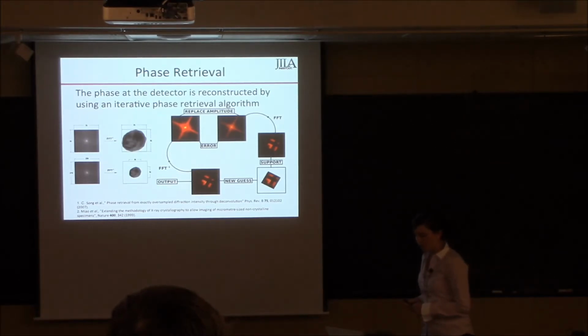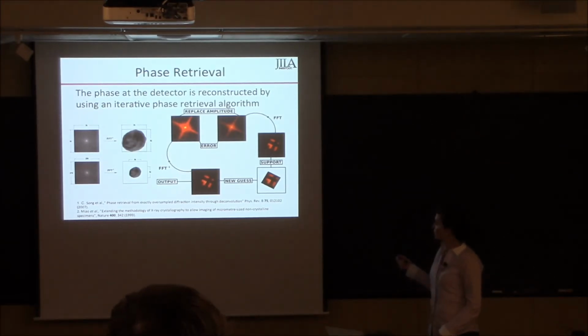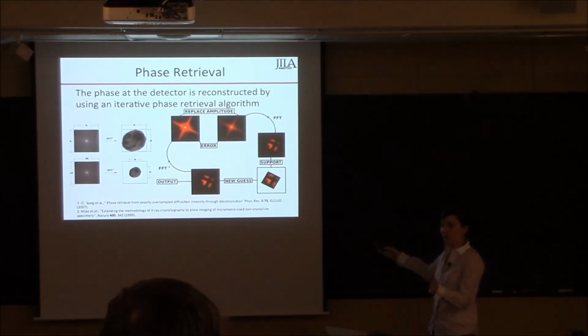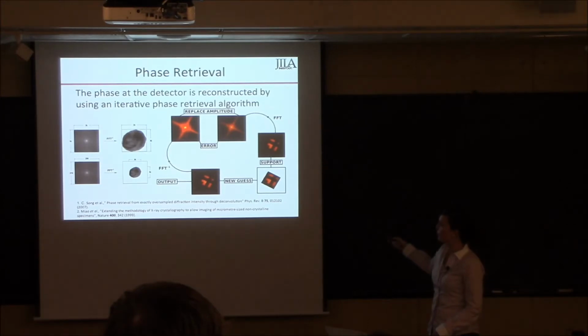So basically what we do is we start with our measured amplitude, which we know because we have a CCD in the far field, and we Fourier transform it to image space, and then we apply the support constraint, which corresponds to setting 3/4 of the image equal to 0, and then Fourier transforming back to Fourier space. And so now we have some possibly goofy amplitude and some phase, right? So we keep the phase because that's what we eventually want to retrieve, but we replace the wrong amplitude with the correct amplitude that we know because we measured.